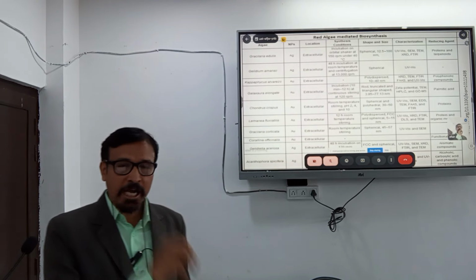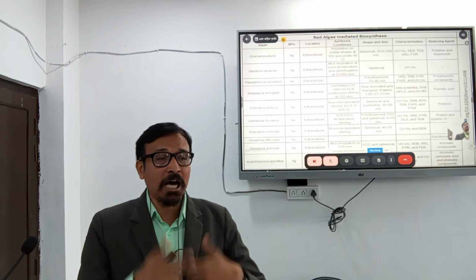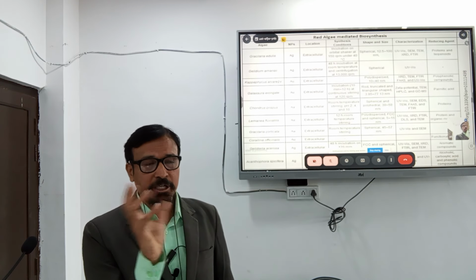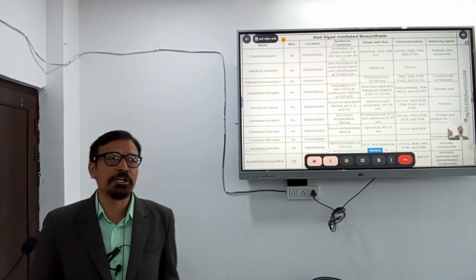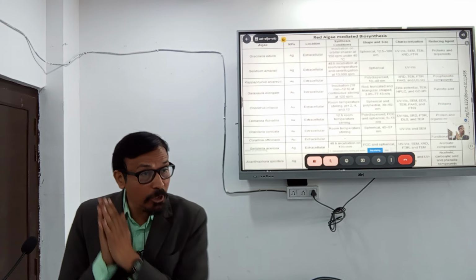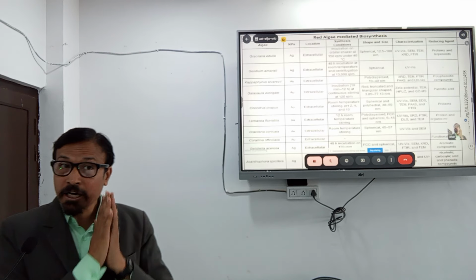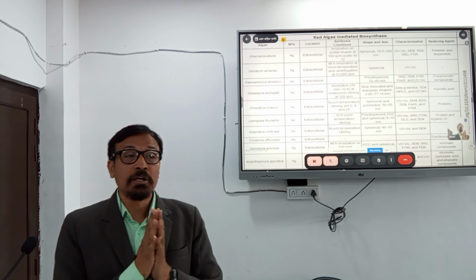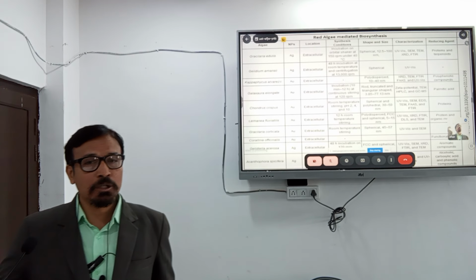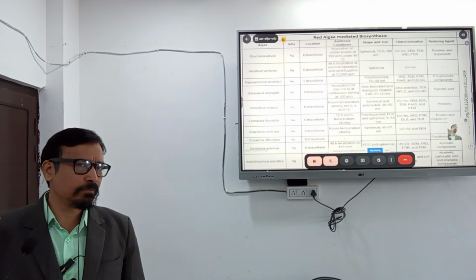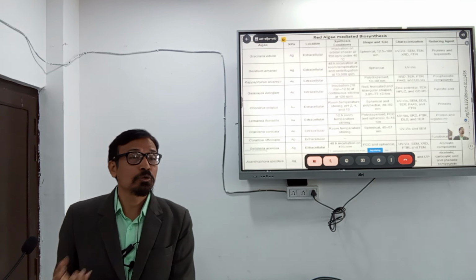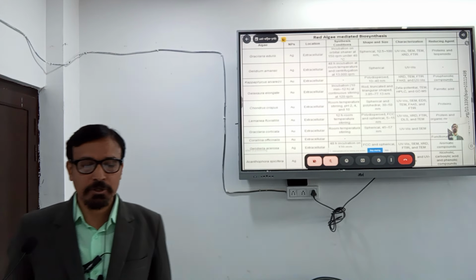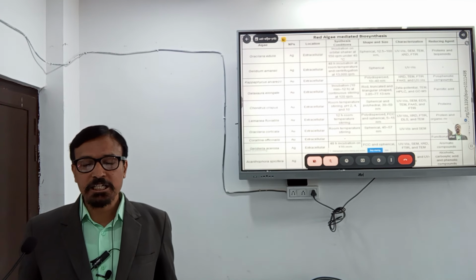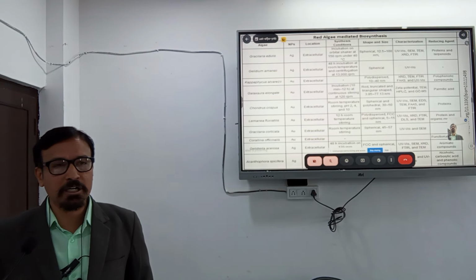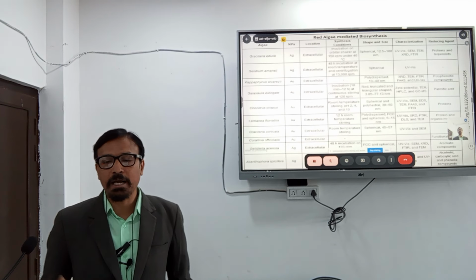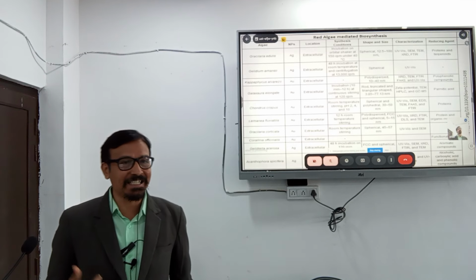So many times we can provide the rpm, so those media will rotate, and only in that condition the silver nanoparticles will be produced. So these are the conditions which have to be fulfilled by us, otherwise the nanoparticles might be synthesized, but those will be of larger size. Okay. So size is spherical and 12 to 100 nanometers, characterization UV-vis, SEM, TEM, XRD and FTIR, and these are the proteins and terpenoids.